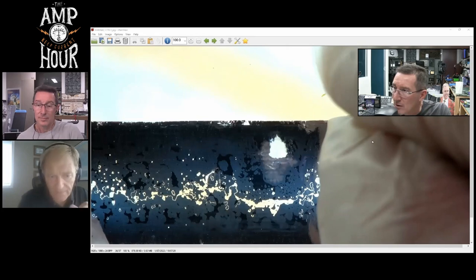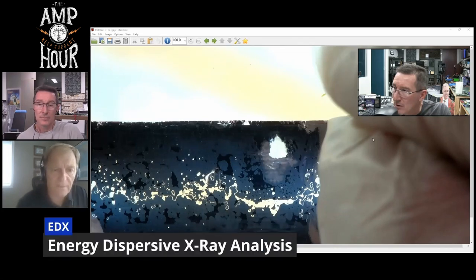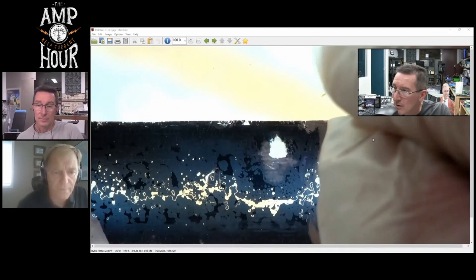Then we'd probably go in with EDX and do some X-ray evaluations of where the material systems have broken down and the constituency of water, etc. And you're not the only one with this opinion. Tom Zednik, if I'm pronouncing that correctly, a former colleague of yours from AVX, who's now over at Passive Components EU, is also of the same opinion that this is a moisture ingress problem and not really an impulse. Because as you said, some of those small little points in there might be self-healing. Is that the size of hole you'd expect from self-healing from an impulse?